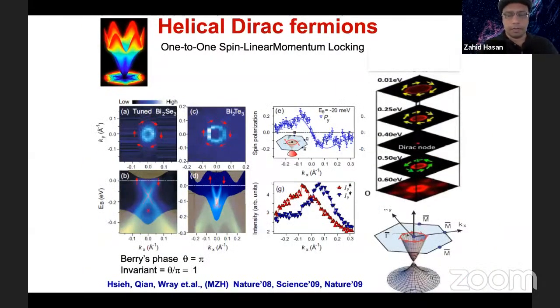Okay, so let me give you a first example of how this technique works with a real sample and what it can tell us. For example, if you take a 3D topological insulator like bismuth selenide or bismuth telluride, as I said, using photon energy change, we can probe the bulk or the surface. If we tune it to probe the surface, then we see this protected crossing on the surface of this compound. And each branch is a spin filter. There are particular spins